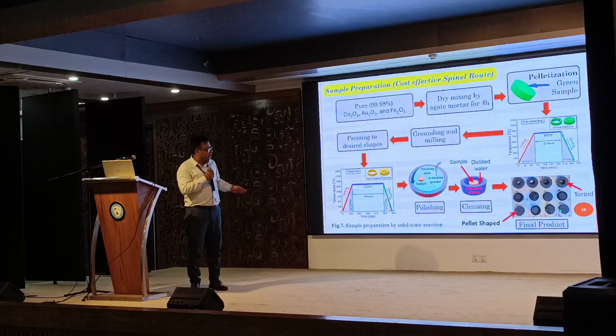Actually, we make two types of samples. One is toroid shape, one is pellet shape, because the toroid shape will measure the permeability of the materials. We can measure the permeability and magnetic permeability, and with the other one we measure the dielectric constant. So in the meantime, we performed another sintering process, that is the final sintering.